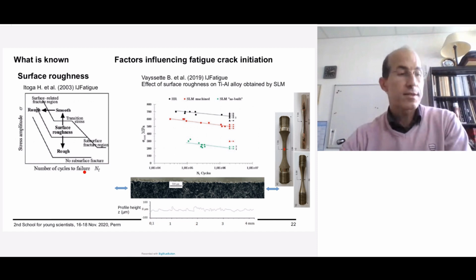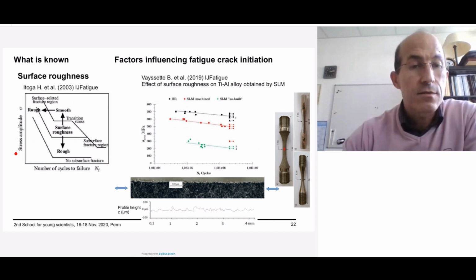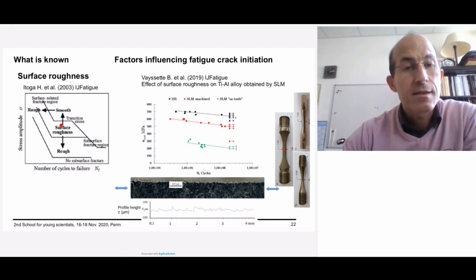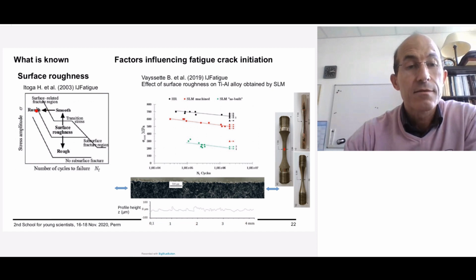Well, first, about the surface roughness. A typical SN curve, stress amplitude versus the number of cycles, illustrated here by Professor Itoga from Japan, illustrates that. So the famous SN curve with different plateaux represents the evolution versus the number of cycles from low cycle fatigue to gigacycle regimes, moving like that. If you increase the surface roughness, it means the profile height, as you can see here, is worse and worse, you will decrease the bearable stress amplitude,